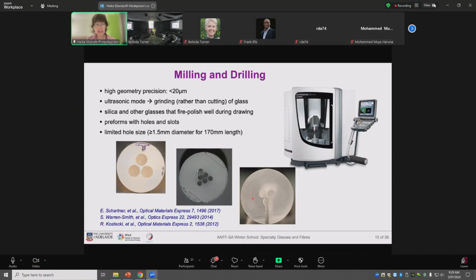Because of the ultrasonic function, the cutting tool is not cutting, but rather grinding its way into glass. This is a gentle way, and therefore a sort of translucent surface is obtained. Of course, you can imagine with drilling and milling, very accurate structures can be achieved. But there's some limitation in the number of holes and the size of holes. So depending on glass type and applications, we use either the milling or the extrusion technique.